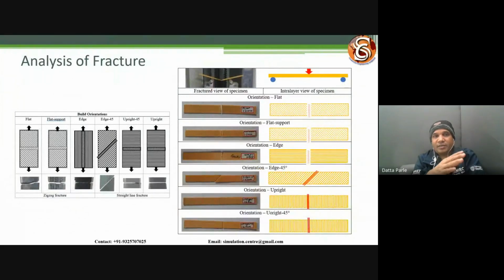And then we also did the analysis of fracture, both in bending and tensile. So if you see, what we observed is, in the case of the flat part which was printed on the bed, it's a more traditional fracture, right? Zigzag kind of fracture, because the part was stronger. Strong groups failed with the zigzag crack, whereas the weak groups failed along the layer direction, because the layers were weak, and these weak layers created easy sites for fracture.